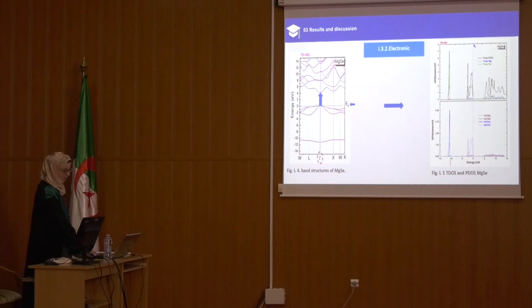For the DOS, the first range from -11 to -10 electron volt is mainly dominated by 4s Se orbitals. For the following range, from -3 to near the Fermi level, we have 4p orbitals of Se, while the last region from 4 to 12 electron volt is dominated by 2p, 3s Mg and 4p Se orbitals respectively.